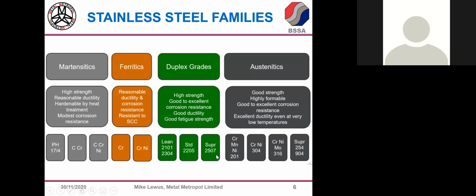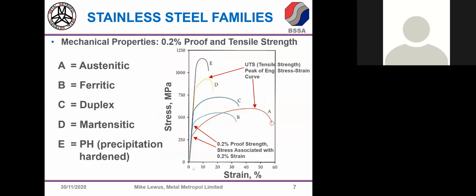I'll probably just draw attention to one thing. The duplex grades, some of you probably already know, duplex suggests two of something. Well, it turns out that the structure of a duplex stainless steel is pretty much 50 volume percent ferritic grains, 50 volume percent austenitic. But rather counterintuitively, it doesn't have properties that lie somewhere between the ferritics and austenitics. They've typically got double the strength of austenitics, and because of certain alloying additions, many of the grades have superior corrosion resistance to the standard austenitics. So already, if you didn't already know, I'm broadening out the range of stainless steels that are available for specific applications. Let's just briefly look at those families in terms of properties.